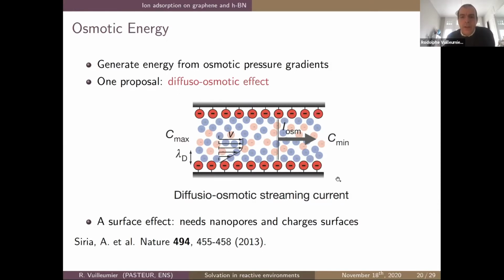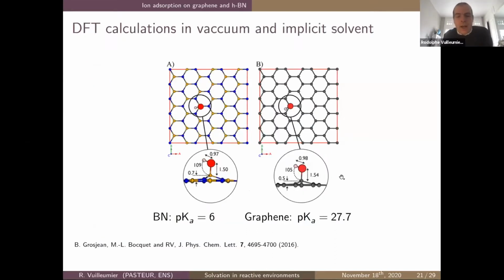So you need surface charges, and we wanted to look at whether this hypothesis of hydroxide being adsorbed on this system is correct. We first did DFT calculations on the isolated surface with an isolated OH minus. We did some of the things that Fabio alluded to in the previous discussion, answering the question of Igor, going from the 0 Kelvin energy calculation to an estimation of the free energies, and we could get a pKa for BN which is exactly in the range that was obtained experimentally, while graphene behaved completely differently, with a much larger pKa. Qualitatively this is the order that you wanted to obtain, but graphene is much too large.